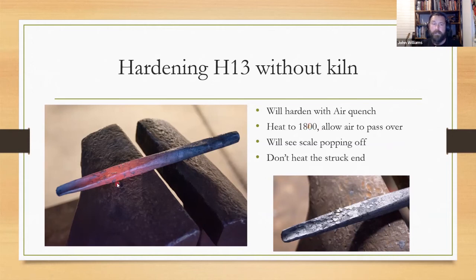To me, I perceive the color as sort of a bright orange, but if you look at the chart, it's not really in an orange range on that chart. Or maybe it is. Maybe I don't perceive color that way. So you can start to ramp it up, but you'll know that it's hardening with H13 if the scale starts to pop off. So scale popping off is a good indication that you're forming martensite. And you always want to have safety glasses when you're working with this steel, because this stuff will fly.